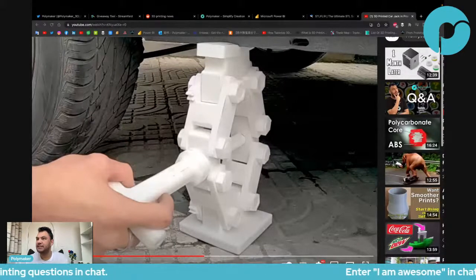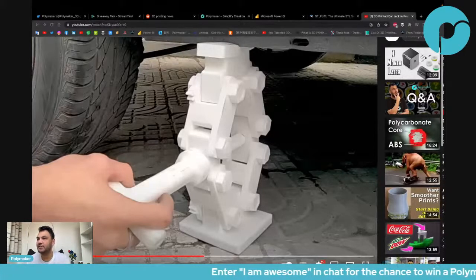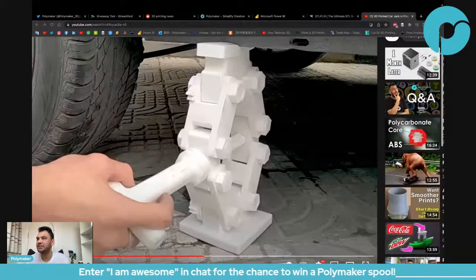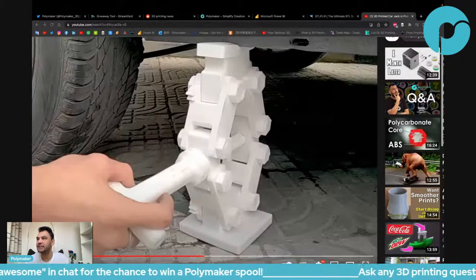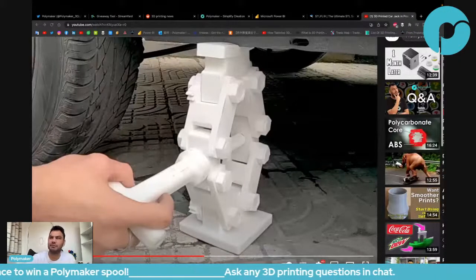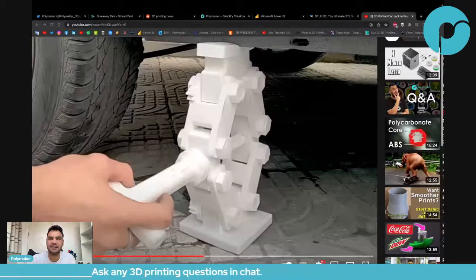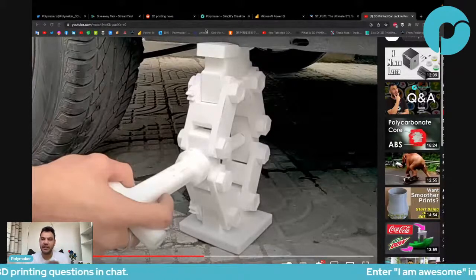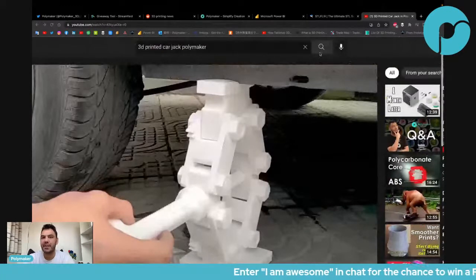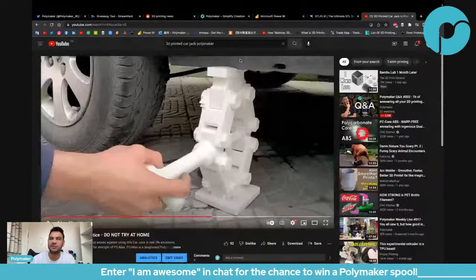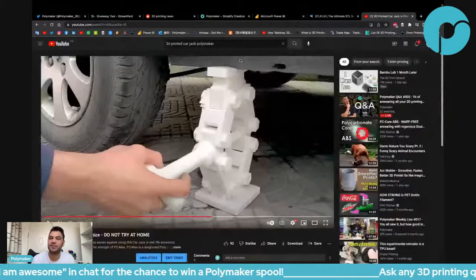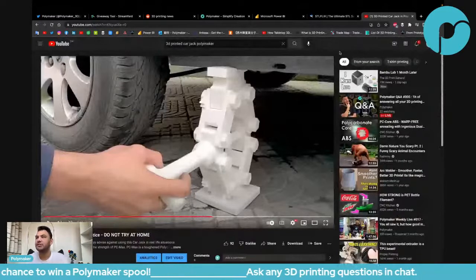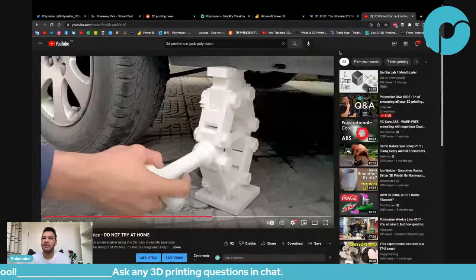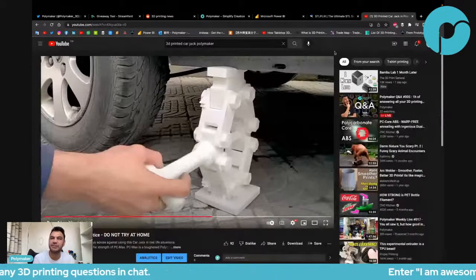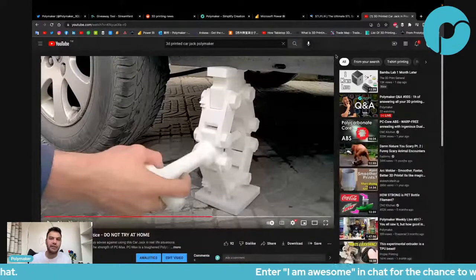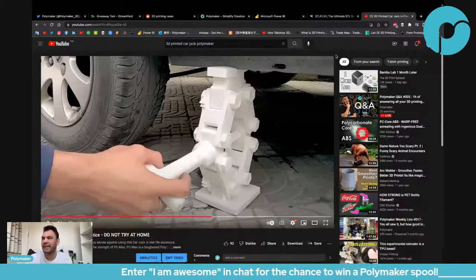Genia, on a previous stream, you said eSUN ABS is cheating. Did I say they're cheating? Is it because of their glass transition temperature being 73, their Polymaker ABS 100-ish, ASA 95-ish? Well, I'm not sure I said they're cheating, but what I said is important to know what's the difference between ABS and ABS Plus. We did some research, and we found out that the HDT of ABS Plus was 73 degrees Celsius, which means the Tg is most likely around 73. So I guess what I said is important to understand is that ABS Plus is more like a PETG in terms of heat resistance compared to a more traditional regular ABS that is more around 100 degrees. I guess that's what I meant.